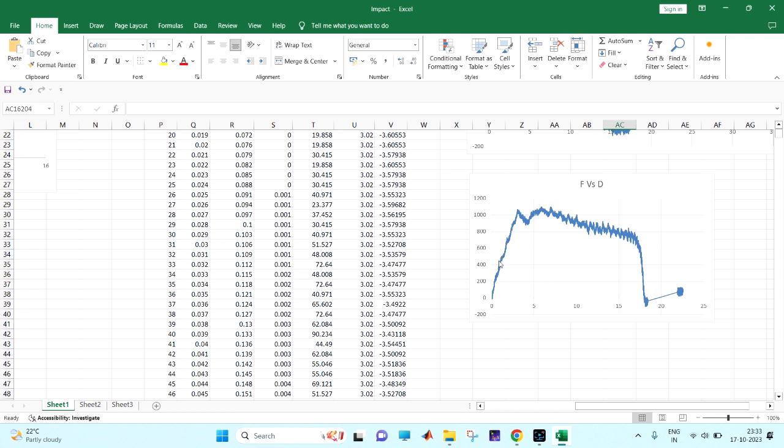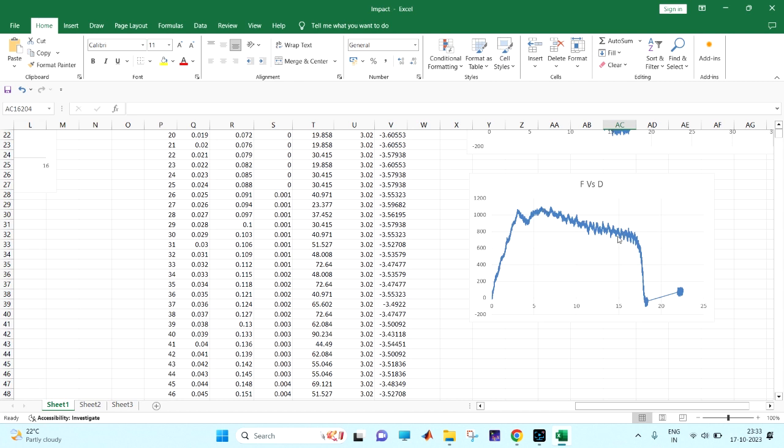That is a very important and beautiful data that I actually want to show you. You can see it here. Actually the initiation damage is initiated somewhere here, before here also at 220, but that has a very less damage. But the main damage is initiated somewhere at the 1014 nearby here, and there is a drop in the force. Drop is not vertical but still there is some drop, and that drop is due to the breaking of the facing. And after that you can see the displacement from here 5 to 15 mm, this is the core compression.